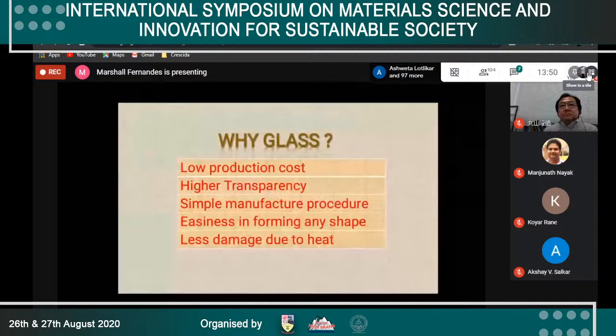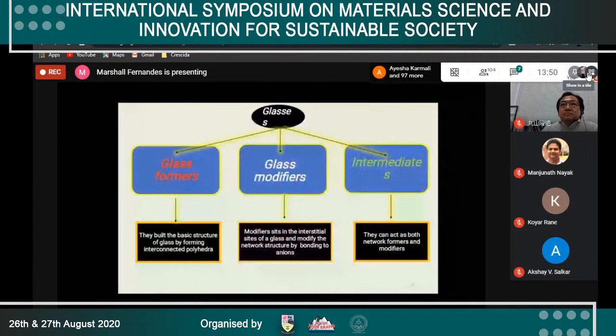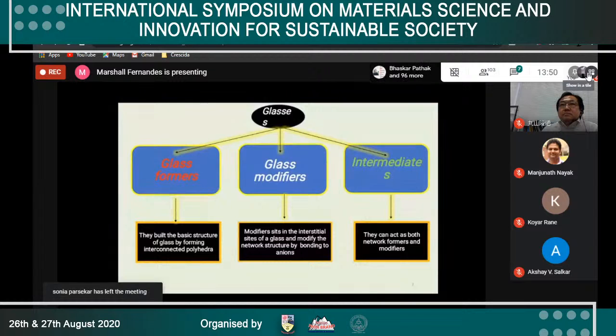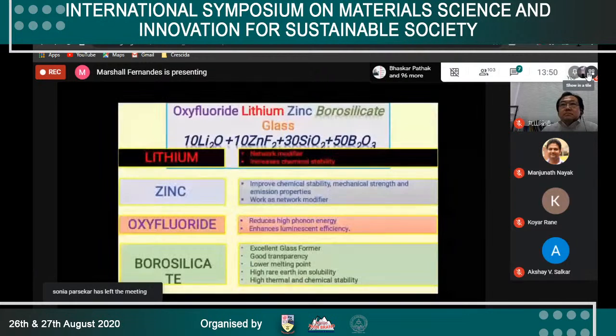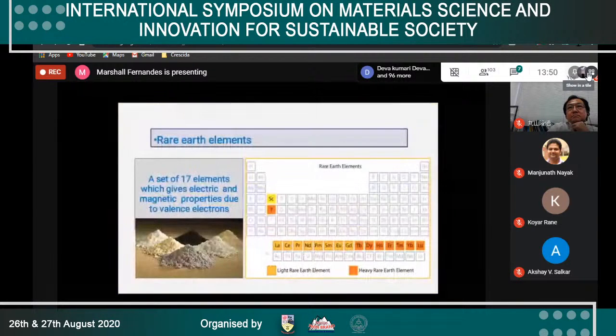Glass basically contains three major parts: glass former, modifier and intermediates. Glass former builds the basic structure, modifier modifies its properties, and intermediates act as network former as well as modifier. In our glass, oxyfluoride lithium zinc borosilicate, lithium and zinc act as network modifiers, oxyfluoride reduces phonon energy, and borosilicate is a good glass former with high transparency and low melting point. So we dope this glass with the rare earth ion to enhance its photonic applications.